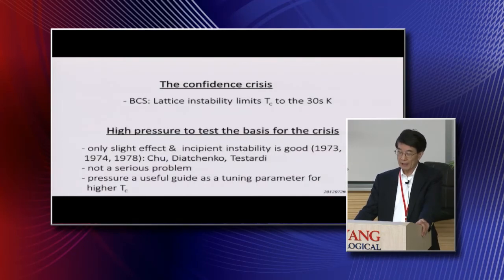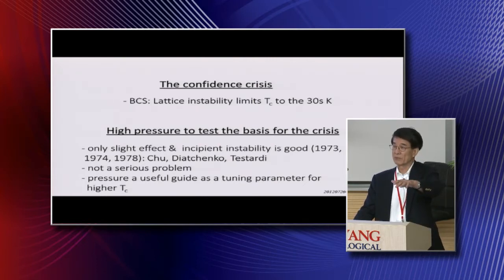So at that time, we decided to look into it using high pressure to determine whether this is indeed the stopper for us to go higher. Because at that time, when we looked at the so-called high TC materials, like niobium-germanium and V3Si, those A15 compounds, when you cool them down, before they get into the superconducting state, indeed, they undergo a lattice instability and transformation. So we decided to control this lattice instability by the application of pressure and try to see whether TC indeed can be raised if we can suppress this instability.